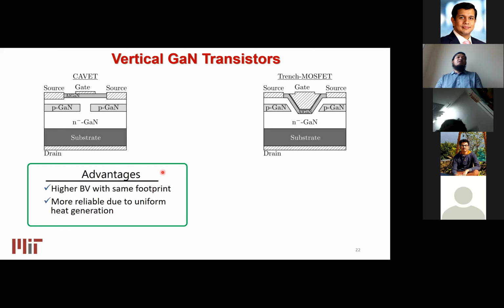The advantages are fairly obvious. Since the current conduction is in the vertical direction, where we have a drain at the bottom and source on the top, we can keep the device footprint the same, but just by increasing the thickness of the device, we can support a higher BV or blocking voltage. And since the current is flowing in the vertical direction, the heat and the electric field are well distributed in the vertical direction, and there is no peak on the surface, so it should have better reliability than the lateral devices.